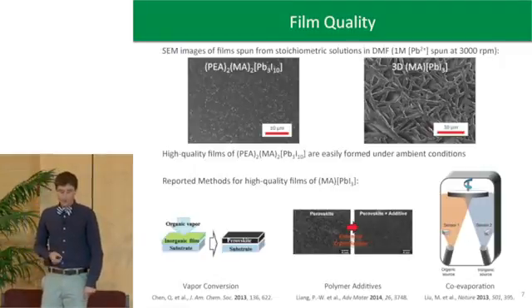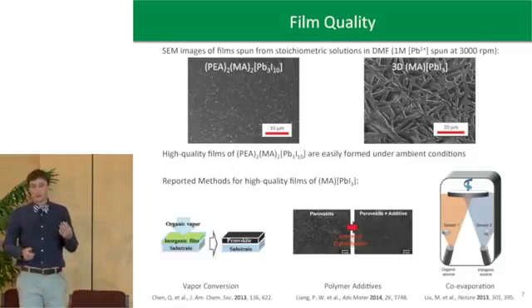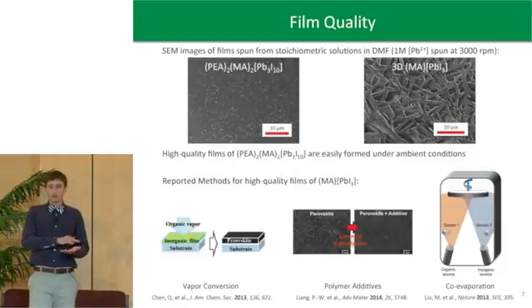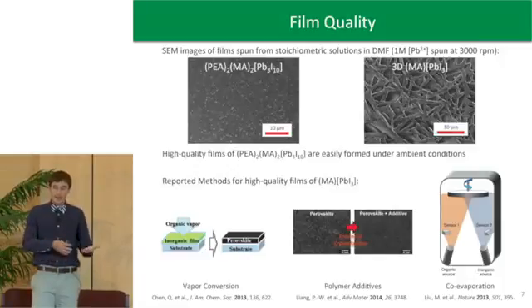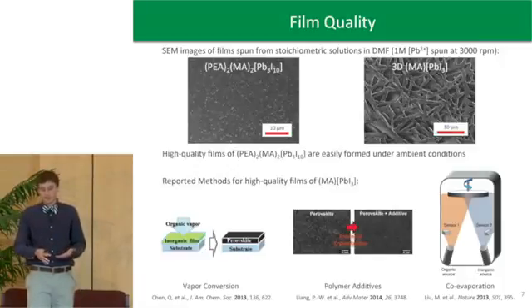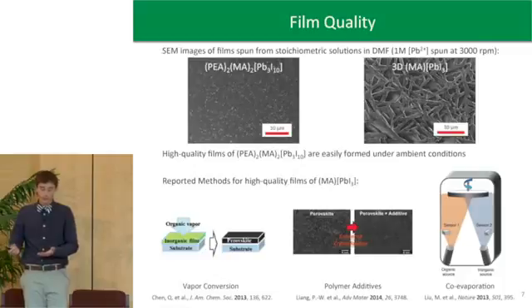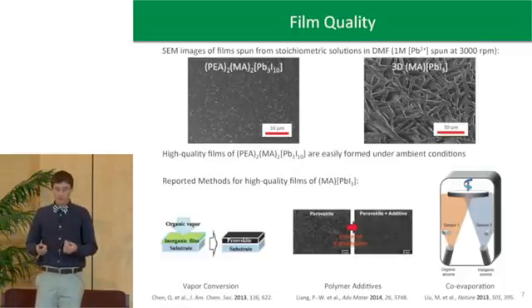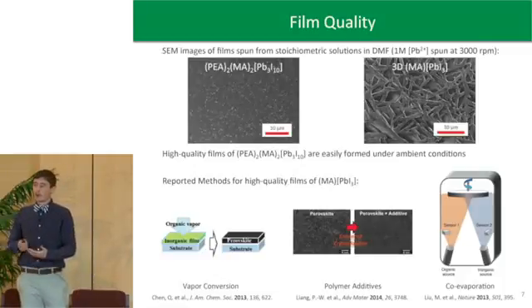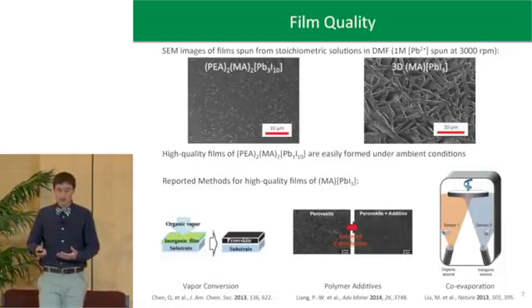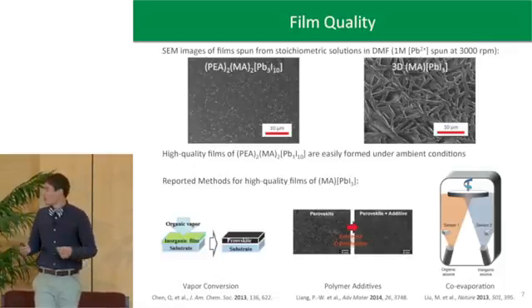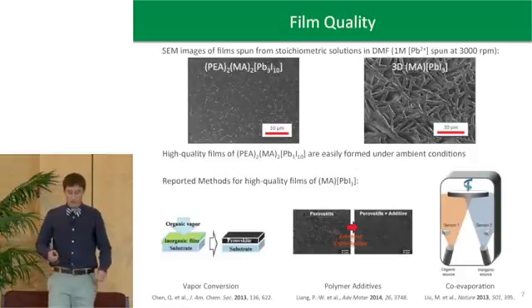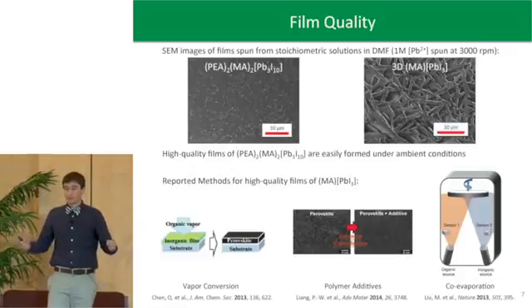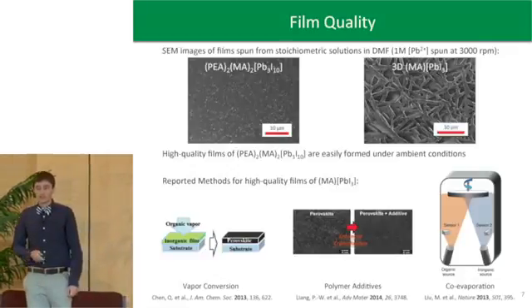There are a few reported out there that I'll mention briefly here. You can start with a lead iodide film, PbI2. That has to start out as a very nice film. And then you convert it at high temperatures using methylammonium vapor. You can also add a polymer to the solution spinning step. Or even you can do a co-evaporation shown here on the right, which is where you have very high temperature sources of PbI2 and methylammonium iodide that in the vapor phase under vacuum will condense on your substrate.